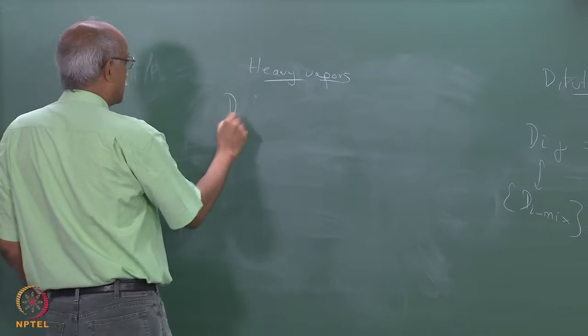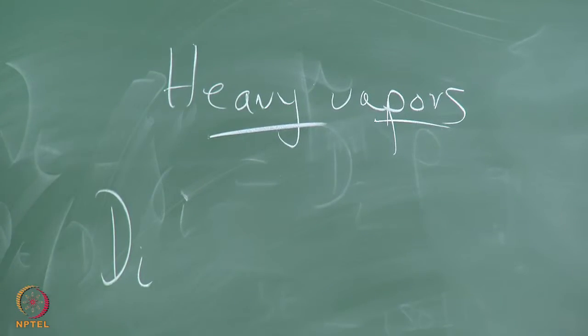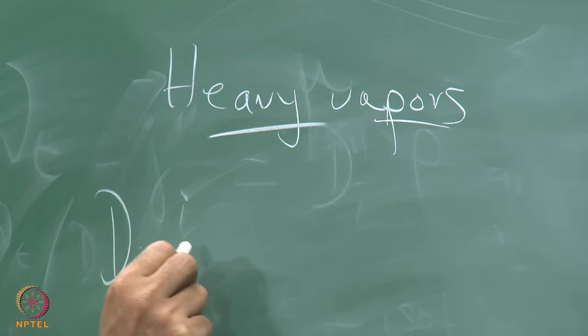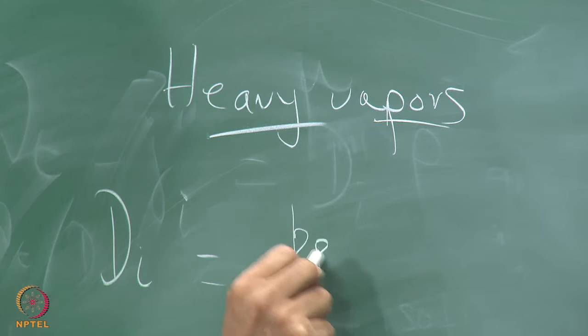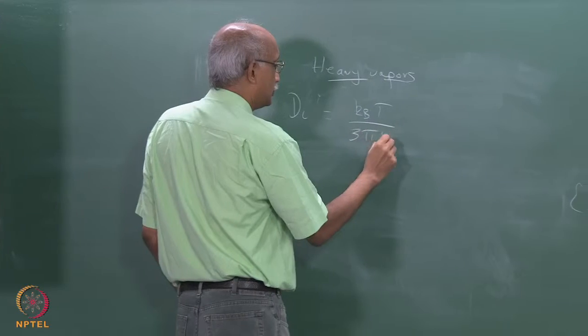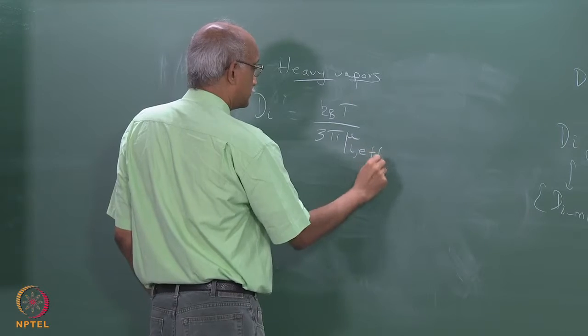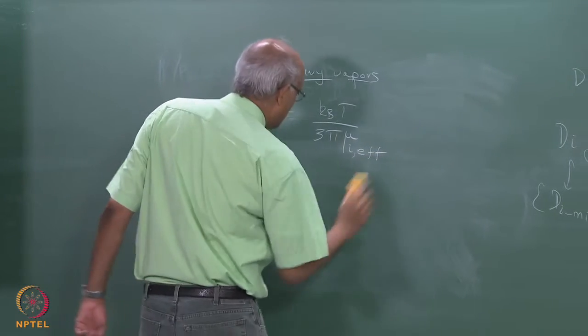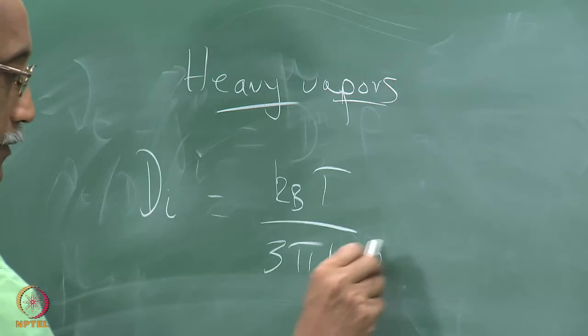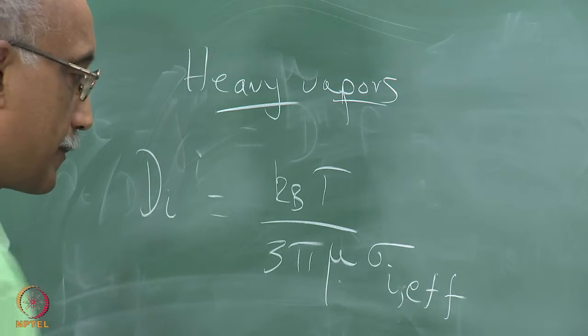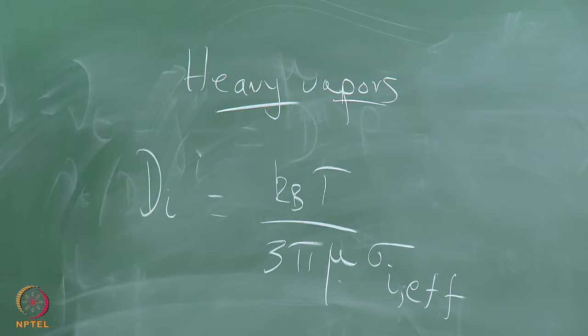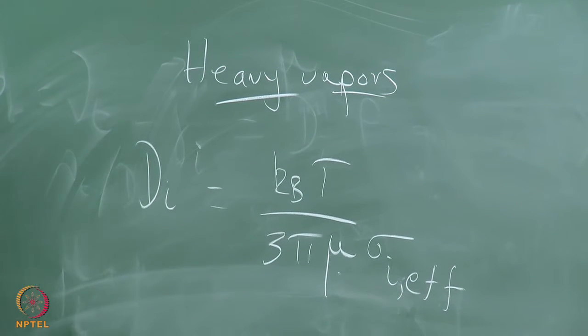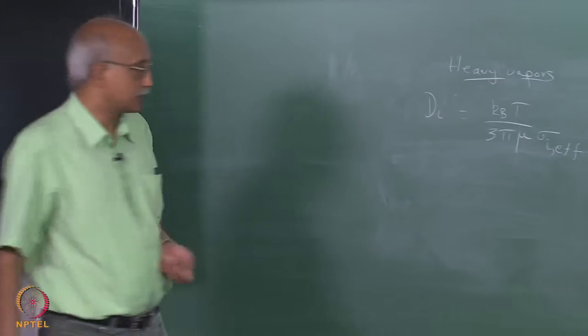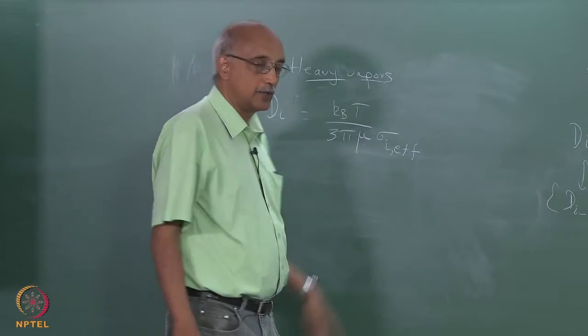The expression for the diffusion coefficient Di equals kBT over 3 pi mu sigma i effective, right. So, in the case of a particle, you would simply substitute sigma with the particle diameter dp, but in the case of a heavy molecule, you use the molecular size. The effective molecular size of the species appears in the denominator.